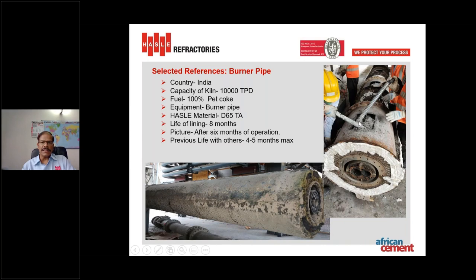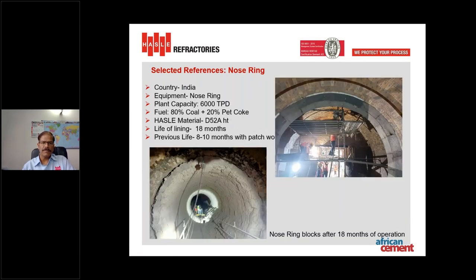This is another burner case story from India. Line capacity is 10,000 TPD. Fuel used is 100% pet coke in main burner. And they were not able to achieve 4 to 5 months life maximum. We supplied our D65TA castable, which is basically corundum based castable, and they achieved the life of, first time, 8 months in this plant. And since last 7-8 years, we are supplying this plant.